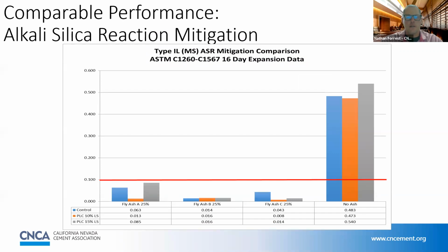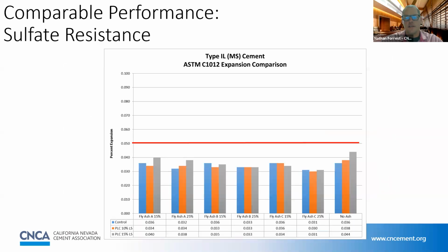We'll take a quick look here at alkali silica reaction mitigation as well. What we have, a little bit different color scheme because this graph is from a different report. We have an ordinary Portland cement mix in blue, a PLC at 10% limestone in orange, and a PLC at 15% limestone in gray. And what you'll see is that with the aggregate selected for this study, none of those cementitious packages mitigated ASR adequately without a supplementary cementitious material, fly ash in this case. But in the presence of fly ash from 3 different sources, all of those cementitious packages did mitigate ASR. So again, comparable performance.